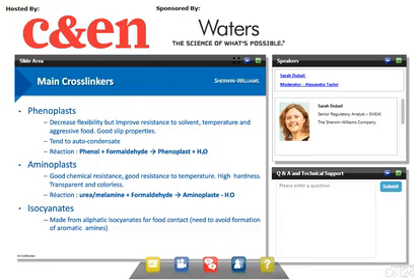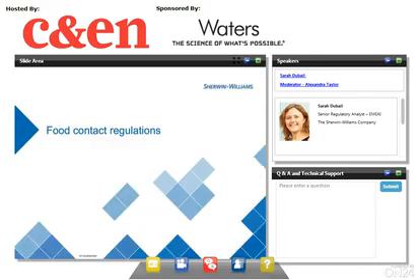Main cross-linker chemistries are phenoplast, made from phenol plus formaldehyde, aminoplast, made from urea or melamine plus formaldehyde, or from isocyanates, as examples. For food contact, note that the isocyanates used are aliphatic isocyanates. As the isocyanate function easily hydrolyzes into amine, it is crucial to avoid formation of aromatic amines for food contact applications.